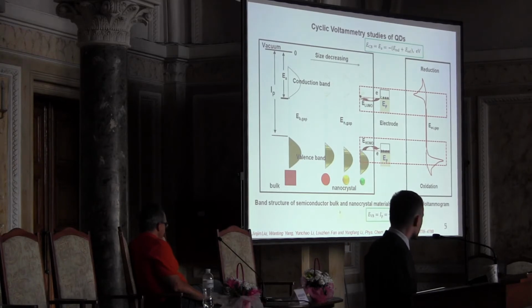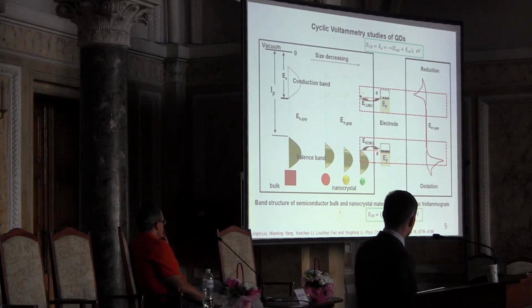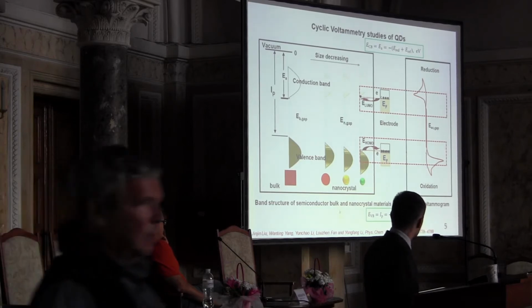Usually, the easiest way is to do it optically, but you can also study them electrochemically, due to the fact that the levels at which you inject electrons correspond either to the LUMO, as you call it, or the conduction band in this case. So as soon as the reduction of the particle starts, it should start at potentials that correspond to this level, and as soon as oxidation starts, you should take away electrons from somewhere, and that's where they usually are in the semiconductor. So you observe the oxidation processes at potentials that correspond to the level of the HOMO or the top of the valence band.